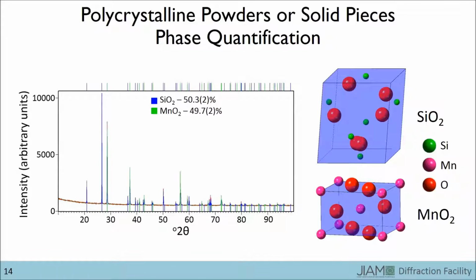The previous slide covered the case in which the material was a single phase. Many times, however, users come to the lab with samples composed of multiple phases. Shown here is the diffraction pattern for the sample containing both silicon oxide and manganese oxide that I showed you earlier. If you look at the unit cells on the right of the screen, you can see that the shapes are very different. Because of this, each phase has a distinct diffraction pattern.